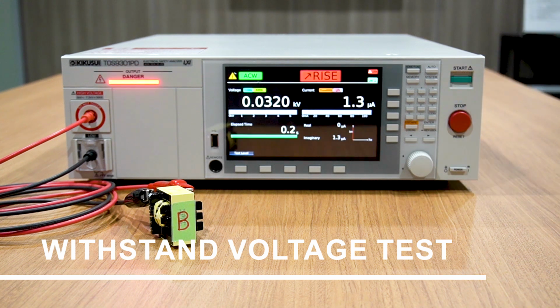Now, let's test sample B. In this case, as you can see, it also measures a current value of 1.3 microamps, resulting in a pass. In the withstand voltage test, it will be judged as a good product. However, in reality, as you can see, partial discharge is occurring and the product has the potential to become defective. But we were unable to detect this phenomenon only through the withstand voltage test.